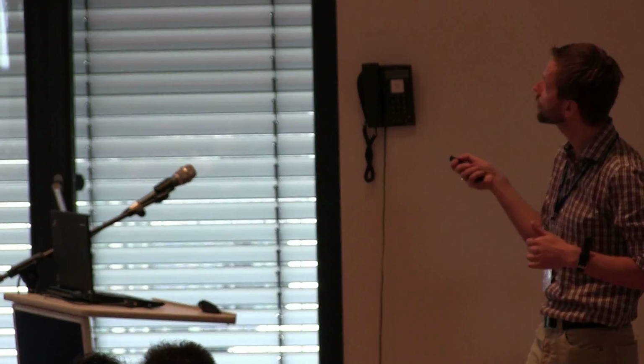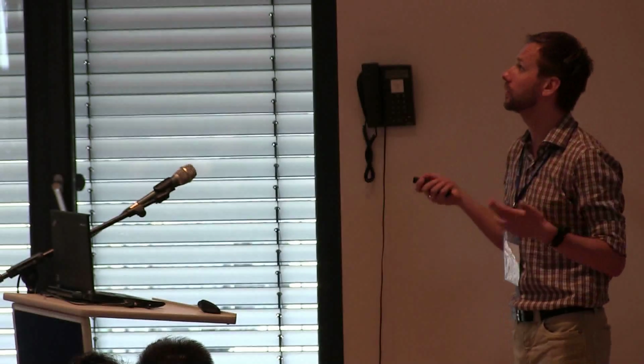In this case, it was graphene sitting on the substrate. Substrate was given in doping, so graphene was conductive. The sigma is the conductivity. So this is just the expression for Ohm's law. So this Terahertz field will drive the currents in graphene. And then the Terahertz pulse that was transmitted through graphene will lose some of its power, which we can also measure in time domain. You see this one is smaller. And this decrease in the transmission means that you have dissipated some energy due to the conduction. You can then analyze the data, and then you can extract all the information you want.